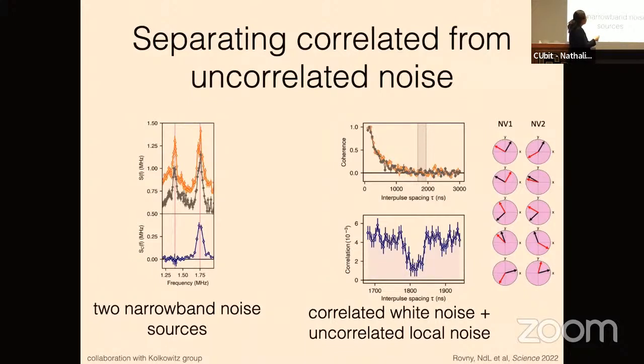The other kind of interesting case that we can look at is that if we apply a very strong white noise signal, we can artificially shorten the coherence time of both NV centers so that they now have a coherence of a few hundred nanoseconds. And normally, if you were trying to do something like nanoscale NMR of these nuclear spins, you would need to operate up here where you still have some remaining coherence. But now, all the way down here in the noise, where you don't have any remaining coherence, because this noise is all correlated, it's white noise that is applied to both of them, it's common mode. Now, if we look in the covariance channel down in here, you can see a little NMR dip that comes from the nuclear spin peak. So this is maybe not dissimilar from the kinds of tricks that people here have been playing with clocks, where you can look at differential channels and then use that to eliminate the common mode noise from your laser.